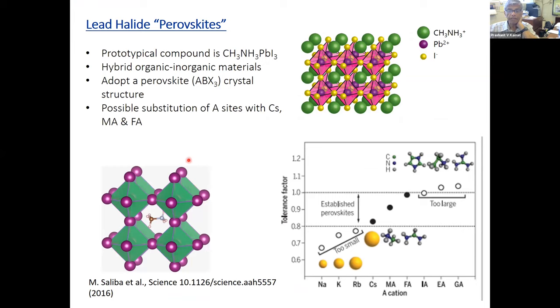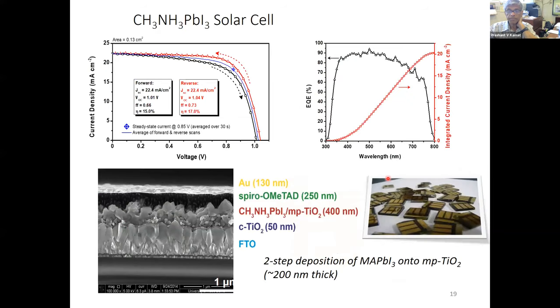The interesting part is this octahedral lead halide structure. There is a cavity in which a cation gets in. In this case, only three cations can be inserted: methylammonium, formamidinium, and cesium. Others are either too small or too large for this to happen.